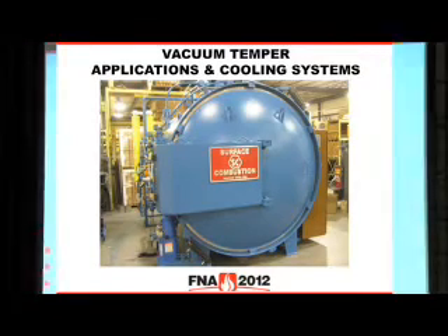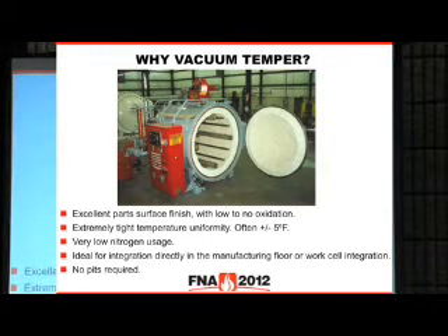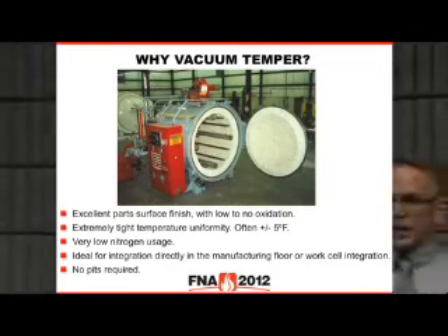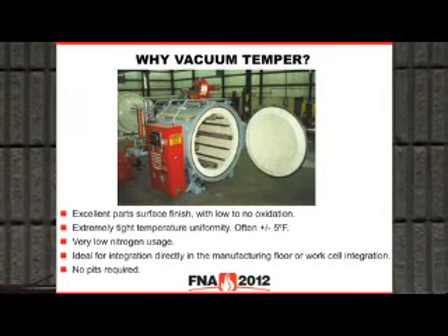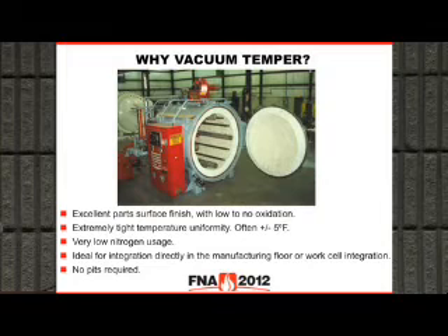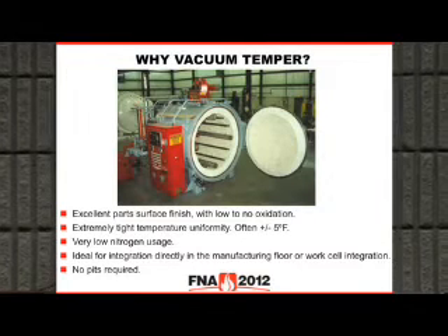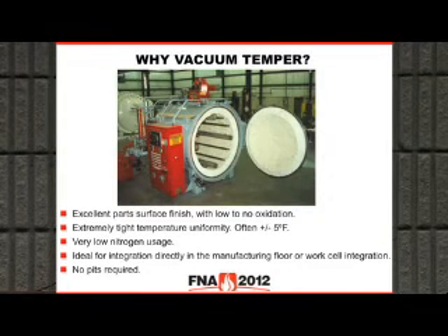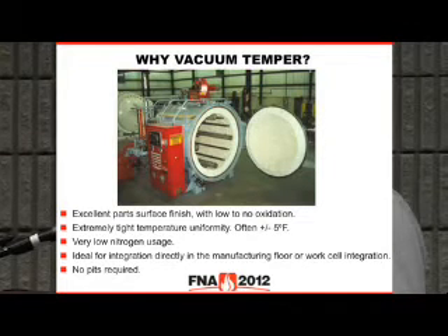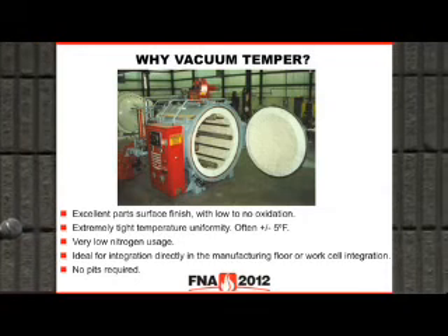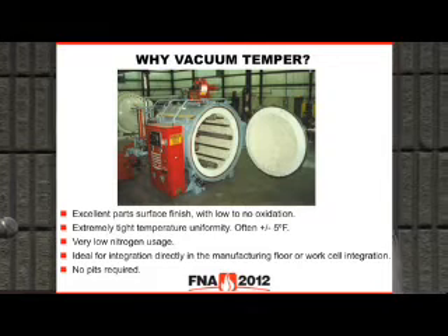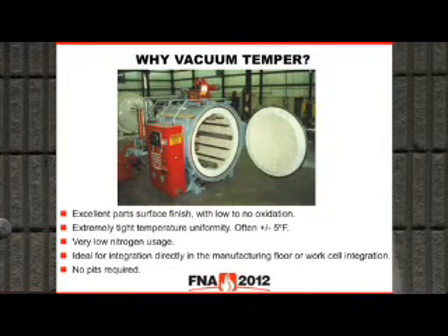So why would you go to the expense of a vacuum temper over just the air and the nitrogen? Number one, part finish. If you have parts that have already been processed in a high temperature vacuum furnace, this material comes out very shiny. Why turn around and put them into an atmosphere temper and discolor them at that point in time? Vacuum tempering equipment, we traditionally see plus or minus 5 for uniformity. Plus or minus 10 is very easy to do, 5 is easy to do, and we have equipment that's even on the order of plus or minus 3 and 4.